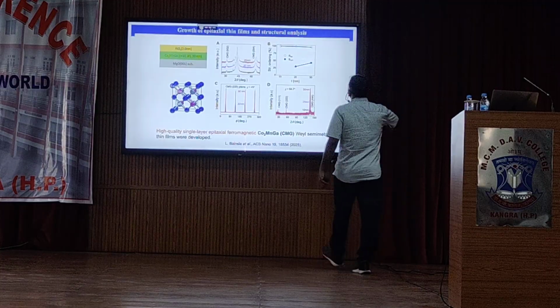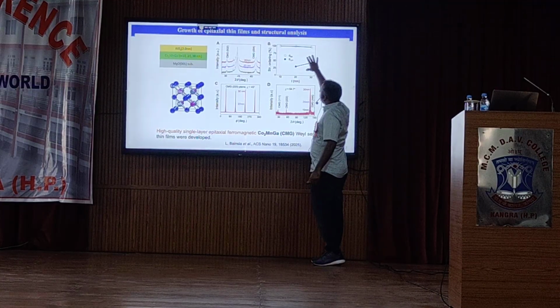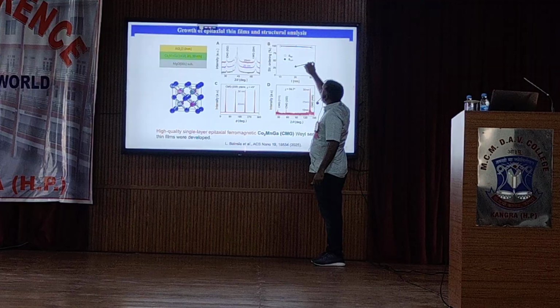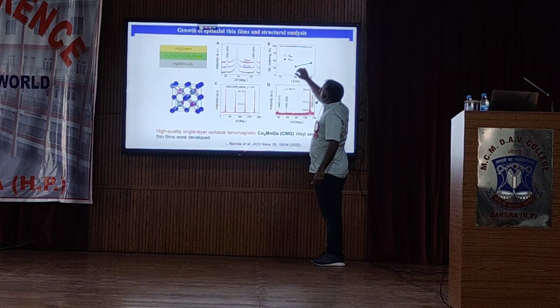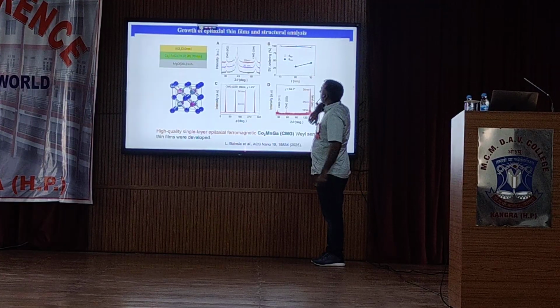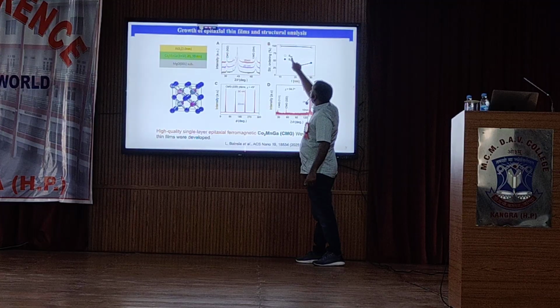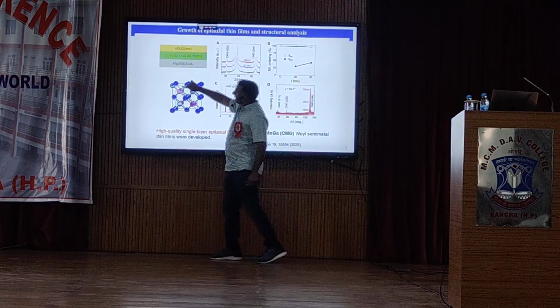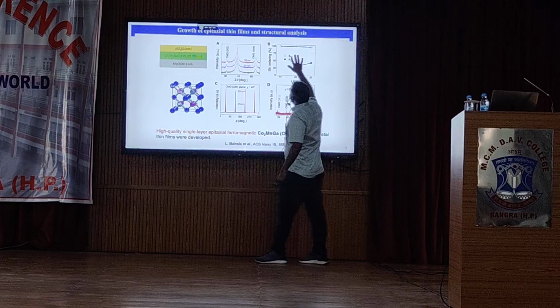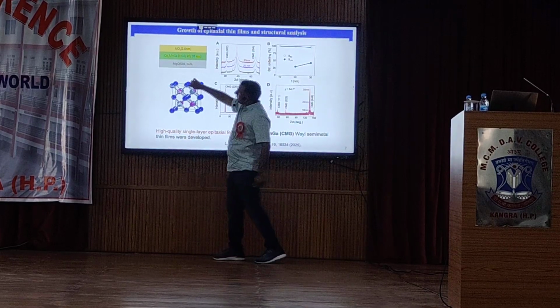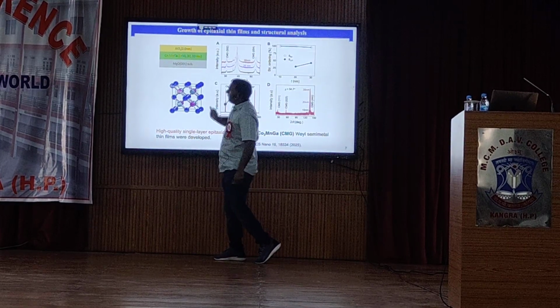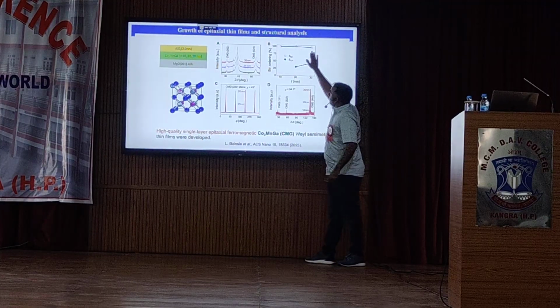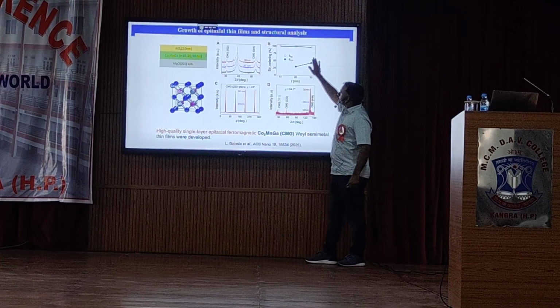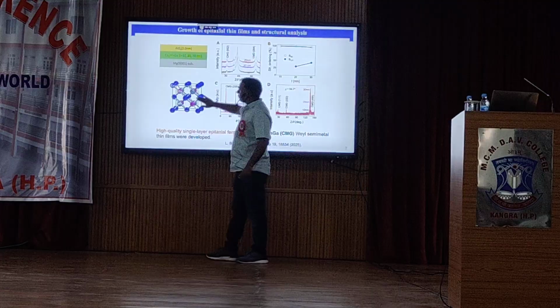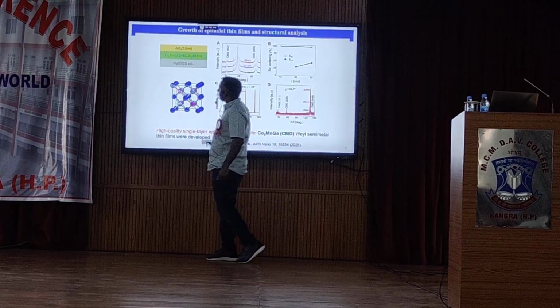And you see here the comparison between our experimental investigation and the theory. Experimentally, if it is a perfect crystal, we expect B2 ordering, which is the ordering between cobalt and gallium. In B2 ordering, we summarize whether there is any disorder between cobalt and gallium. And as you can see here, we have almost perfect B2 ordering. So there is no disorder between cobalt and gallium sites.